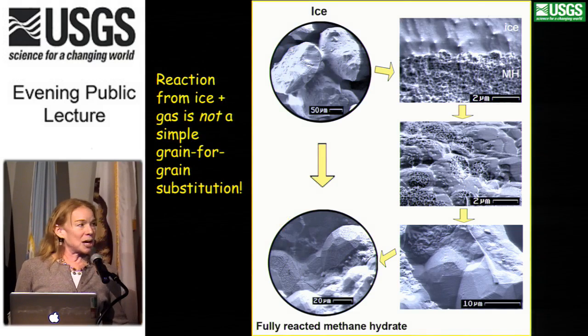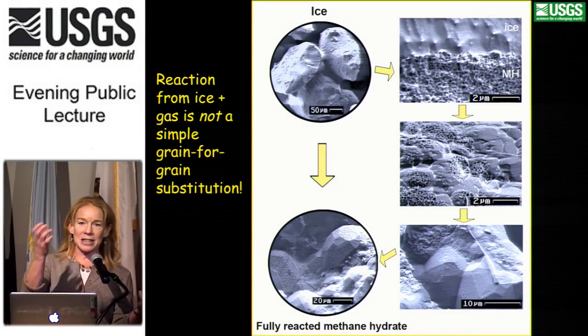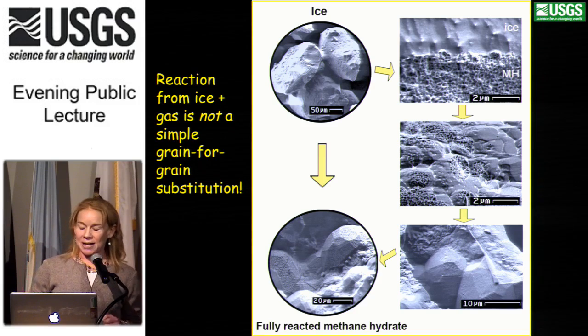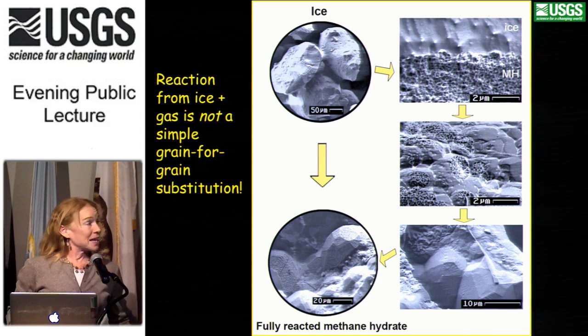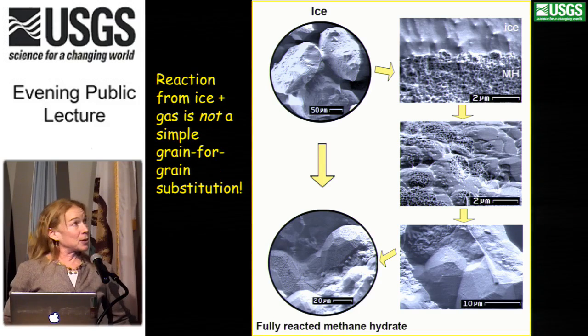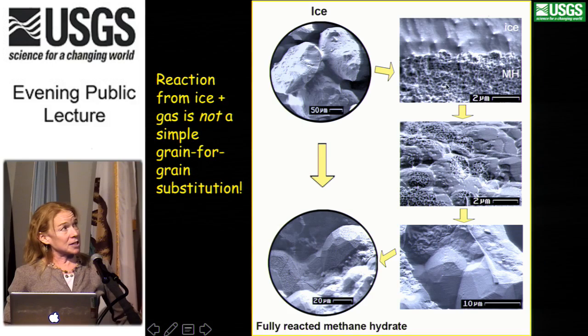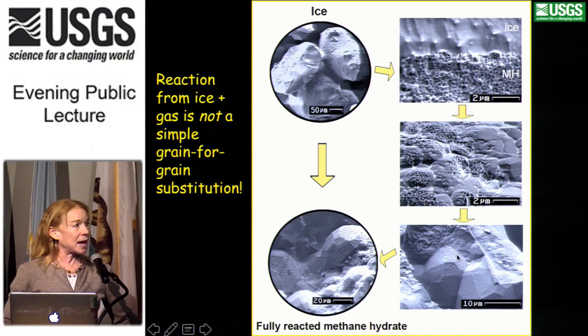We originally thought, prior to getting a cryo stage here on campus, that the reaction from ice to methane hydrate was a grain-for-grain transformation. And boy, were we wrong. What we found was actually that the reaction process starts on the outside of the ice grains up here. It starts mesoporous, spongy looking at first. But this is just a 2-micron scale. Then we develop these very small subgrains that continue to anneal during the synthesis of the hydrate to create these beautiful, fully formed methane hydrate crystals in the final texture.